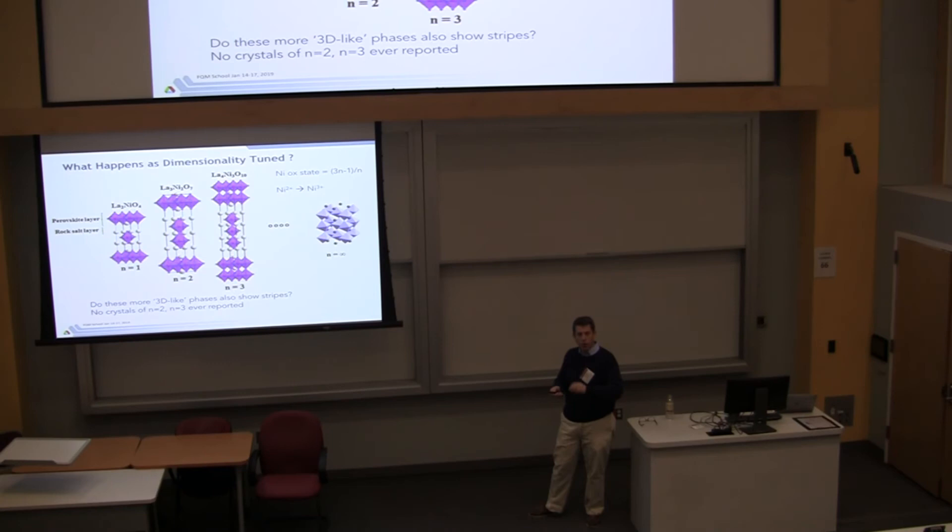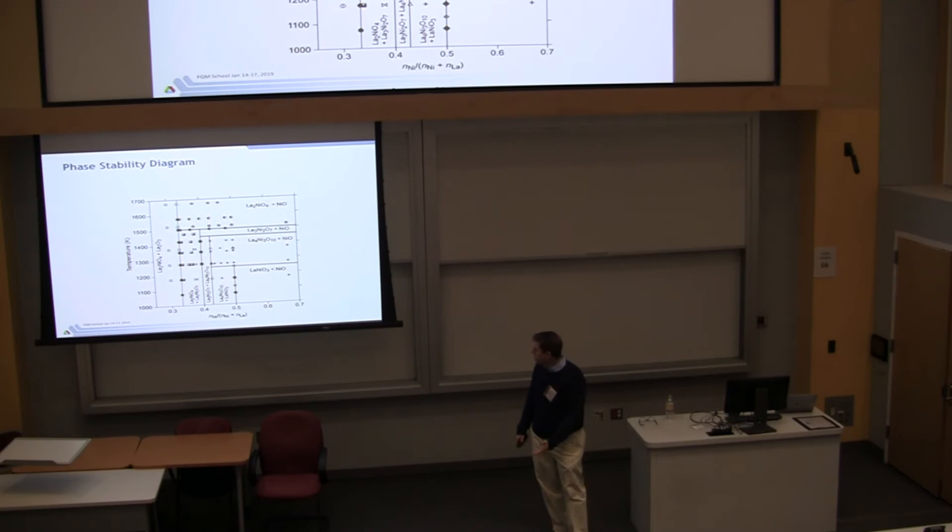Here's the two-layer material, however. And now you see, just like in the cobalt oxide I showed you a minute ago, calcium cobalt oxide, this stuff decomposes. So does the three-layer material, and so forth and so on. And so does the perovskite. So all these materials, they're also landlocked. No liquid in sight. So what happens? Well. Obviously I wouldn't be talking about them if we couldn't grow crystals. So we put them in the high pressure furnace. We started out wanting to grow this material, this lanthanum nickelate 3.